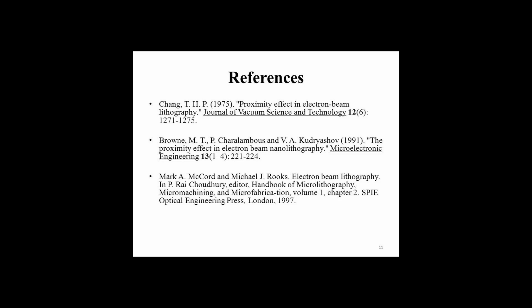The cross-section for electron attachment is inversely proportional to electron energy at high energies, but approaches a maximum limiting value at zero energy. On the other hand, it is already known that the mean free path at the lowest energies, a few to several eV or less, where dissociative attachment is significant, is well over 10 nanometers, thus limiting the ability to consistently achieve resolution at this scale.